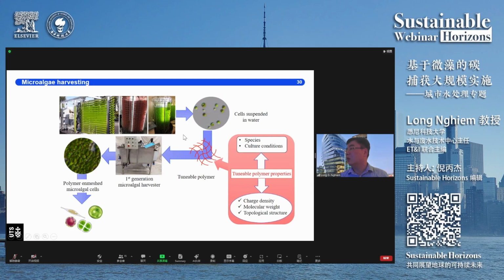So overall, when we look at some fundamental questions such as how we can optimize the flocculation by polymer for microalgae harvesting, we can see clearly that basically it's a rather simple process. We need to have a sufficient molecular weight so that the polymer can act like a spider web, but it needs to be sticky. So we need to have a highly positively charged polymer so that at the end we have a very sticky spider web that can aggregate the individual cells.